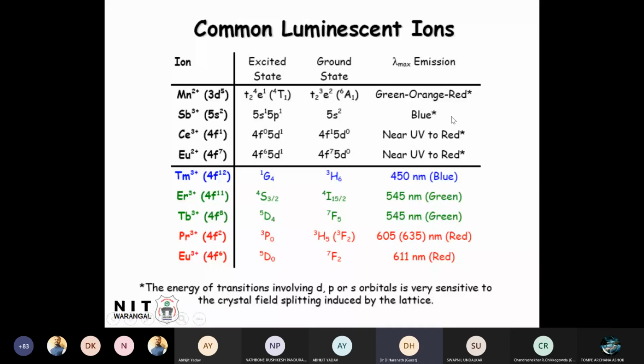That's why asterisk stars have been put here, and here it is written. It is called crystal field splitting. Means the host crystal will have some influence, like the Zeeman and Stark effect you might have studied. Zeeman effect is the splitting of spectral lines in the presence of a magnetic field, and in the presence of an electric field, it is the Stark effect. Is it not? So similarly here, if you are doping in certain crystals and the crystal is influencing its emission, then you can get different colors. That is called crystal field splitting. In very few ions it will show like this, like antimony blue and cerium from UV to red, any color, depending upon the influence. More influence, more towards red. Less influence, towards the left-hand side.